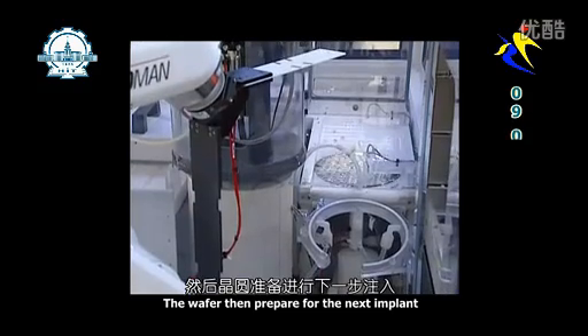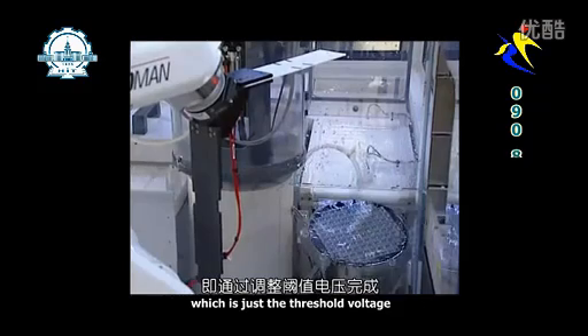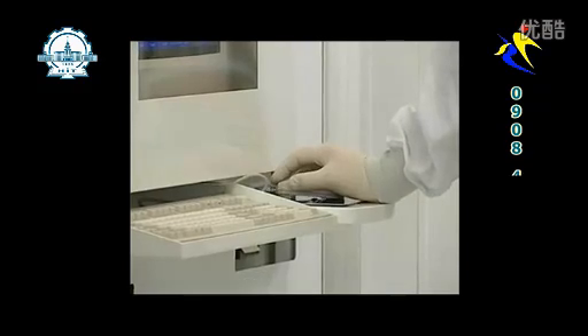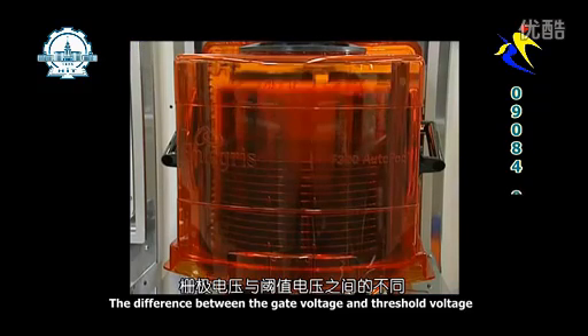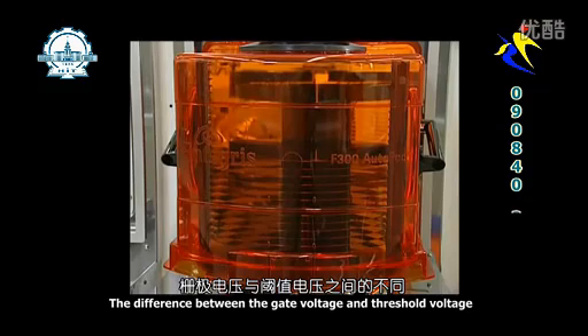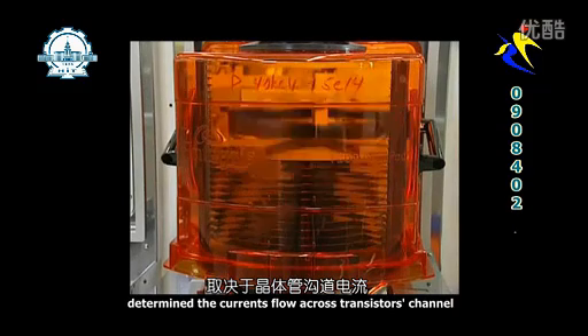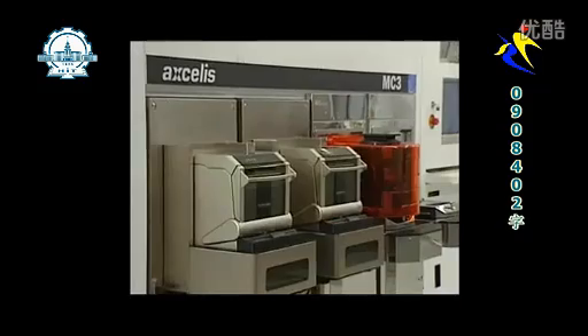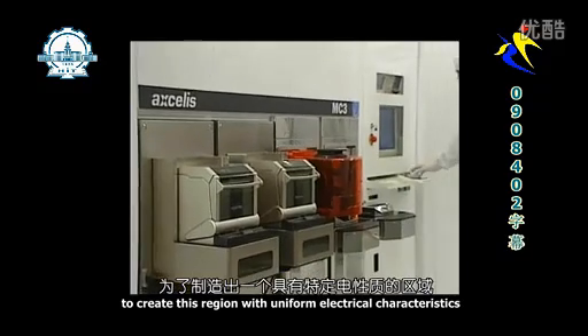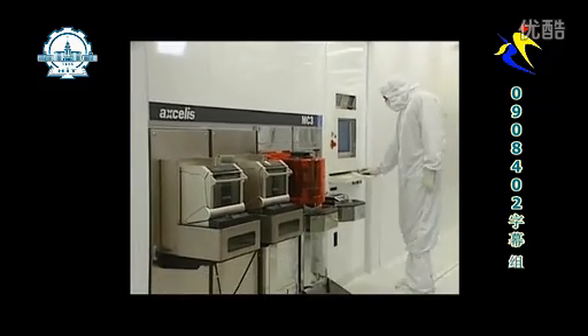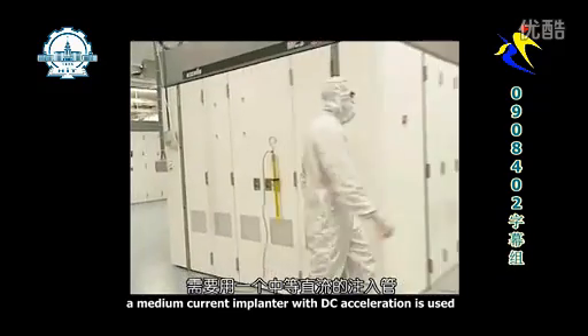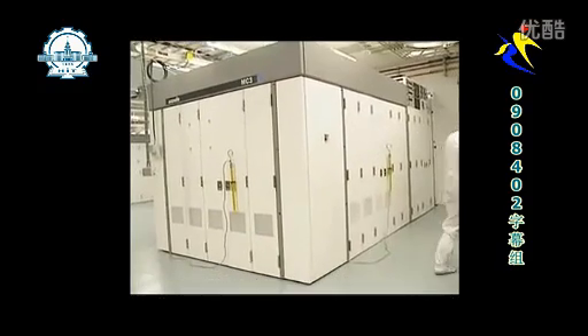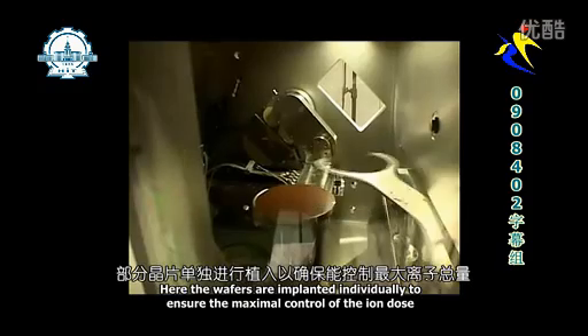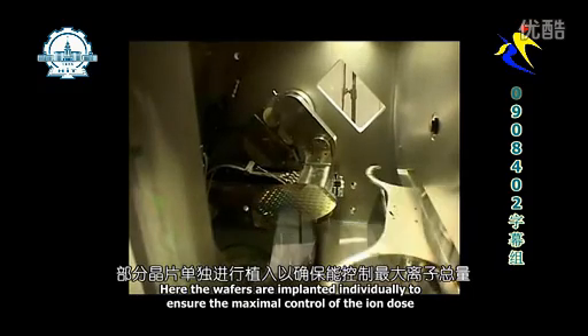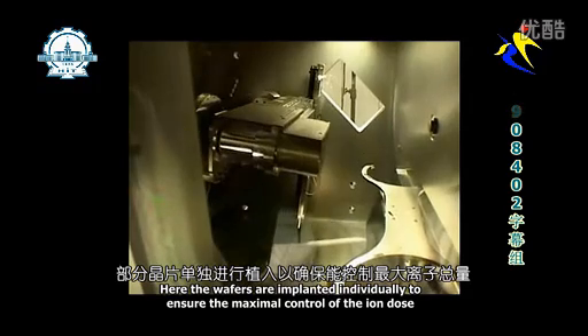The wafers are then prepared for the next implant, which adjusts the threshold voltage. The difference between the gate voltage and the threshold voltage determines current flow across a transistor's channel. To create these regions with uniform electrical characteristics, a medium current implanter with DC acceleration is used. Here, the wafers are implanted individually to ensure maximum control of the ion dose.